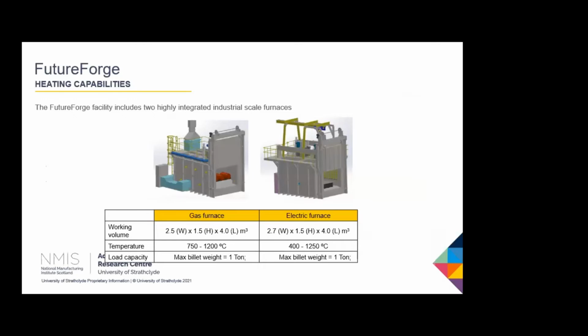This, I think, is really the important point here. These are the 2 furnaces that we have available: effectively a gas-fired furnace and an electric furnace. The gas-fired furnace has an operational range in the order of 750 to 1200 degrees C, whereas the electric furnace has an operational range between 400 and 1250. Between 400 and 650, we've got a fan, so we can get fan-assisted heating and a uniform temperature. Above 650, we have to take the fan out because otherwise it'll melt, and we'll have a slightly different non-uniformity in temperature. But again, that's important in terms of comparing and contrasting the energy transition towards electric furnaces.